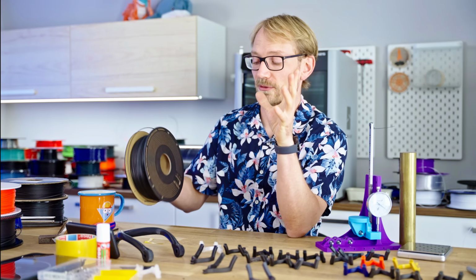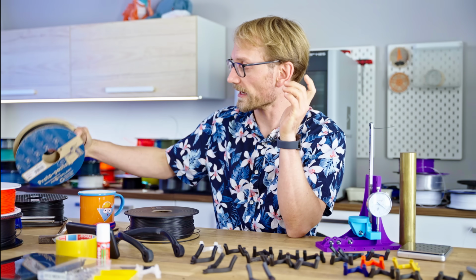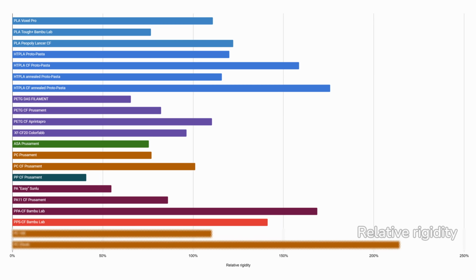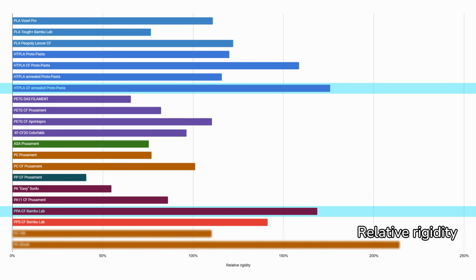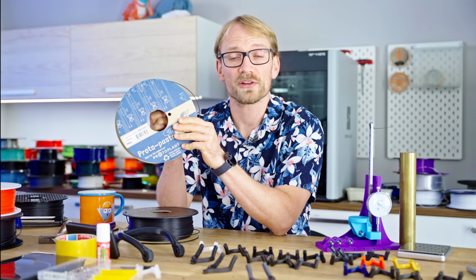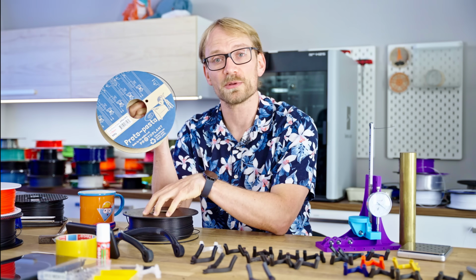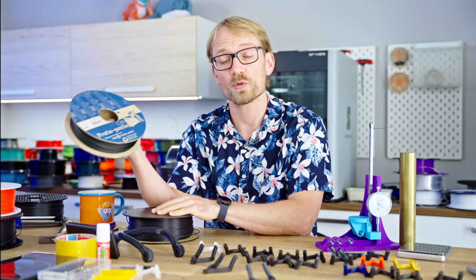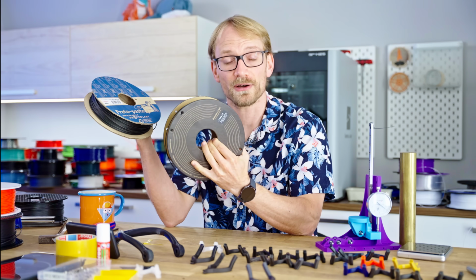Unless you also count the HTPLA-CF once it has been heat treated, because this actually does produce parts that are slightly stiffer, slightly more rigid than the PPA-CF. And interestingly, it does it with an extra post-processing step, but it does it at just over 1/3 as much per kilogram as the PPA-CF. So this gives you more rigid parts at a fraction of the cost.